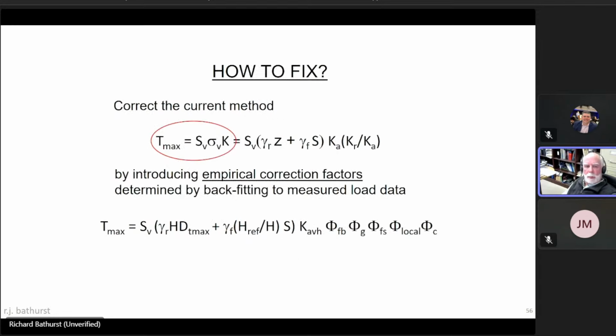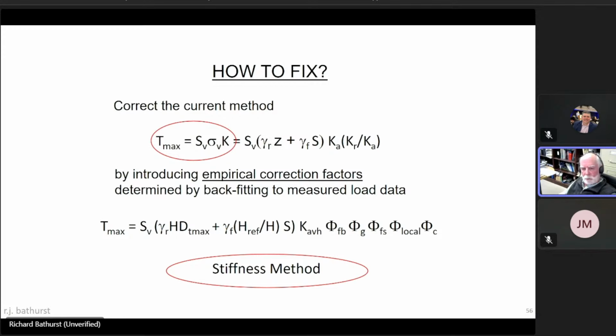How to fix? Well, the current simplified method is shown by this equation at the top here. And so what we did, I guess in a way, we borrowed from the structures guys, and we took this equation at the top, and we modified it by introducing correction factors that you can see in this lower equation. These phi terms are all empirical, non-dimensional correction factors.